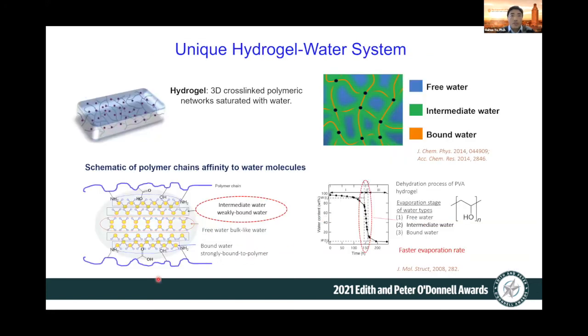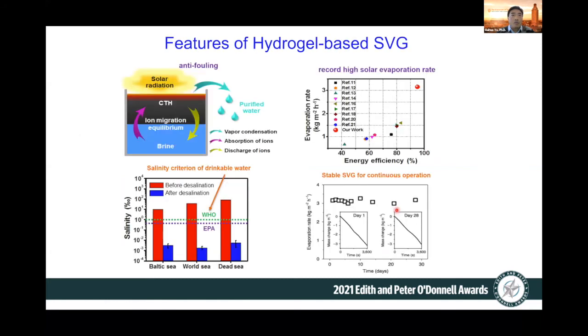features. One of the key features here is the regulatable hydrogel-water interaction. As we know, hydrogel is a 3D cross-linked polymer network saturated with water. There are three different water states involved in the system. You have the free water shown here, and the intermediate water is in between the free and the least closely bound water. This intermediate water actually requires less energy to evaporate. That was experimentally observed in our system before, and we demonstrated for the first time using the hydrogel for this anti-fouling solar vapor generation.